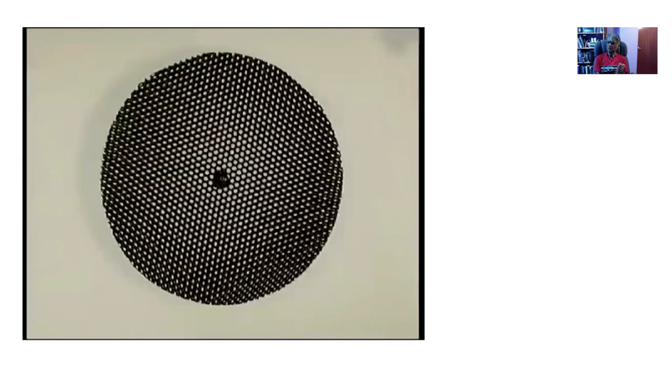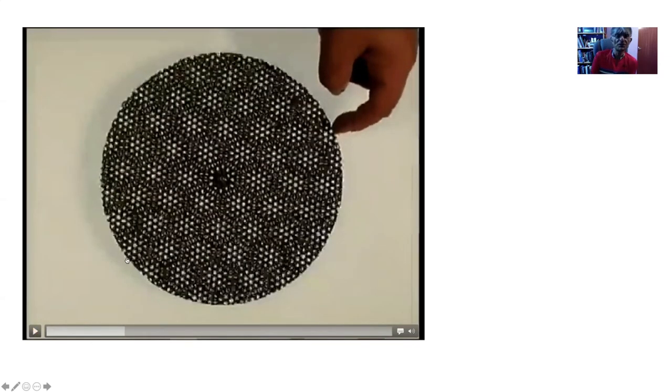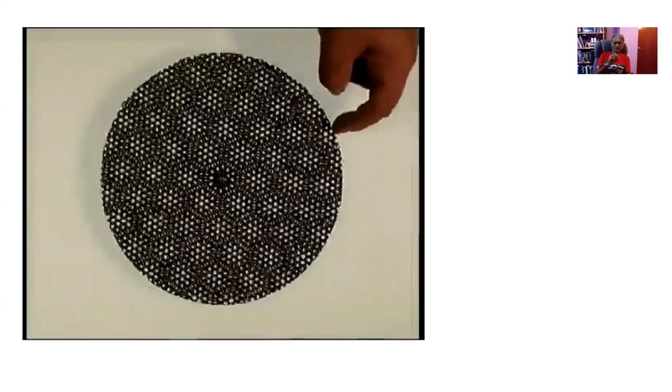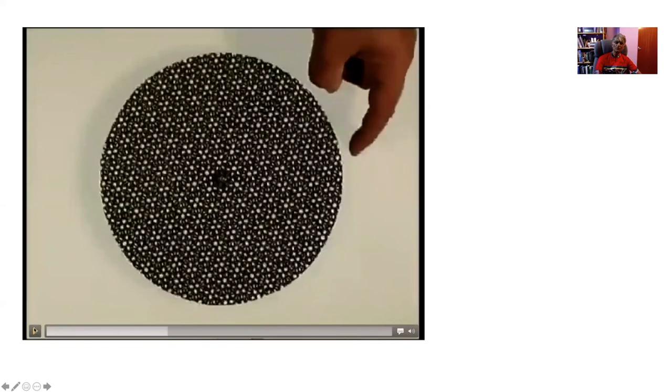And in this case, I'm using two-dimensional crystals, a pair of hexagonal crystals, and they share a common origin. So when I change the misorientation, you see some interesting things happening. So here, for example, if you look at this orientation, there are points which are in exactly the same place for both of the lattices, as you can see here, okay? And furthermore, if you look carefully, these coincident points actually make a pattern. And that pattern is different for different misorientations. So here, for example, is another pattern with a higher density of coincidence points, and so on.